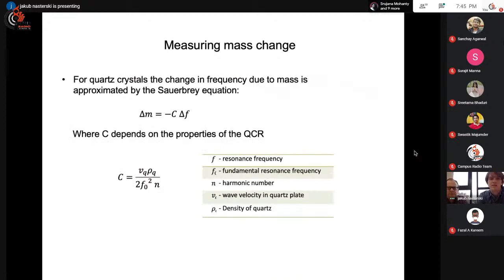Then, when we measure those frequency shifts, we can directly use them to calculate the mass of the copper deposition using what's called the Sauerbrey equation. We just need to know the properties of the quartz and the frequency shifts. And then obviously if we have the mass, we can just divide it by the area of the deposition, and we can get the thickness. So that's one basic simple application of the quartz crystal microbalance.